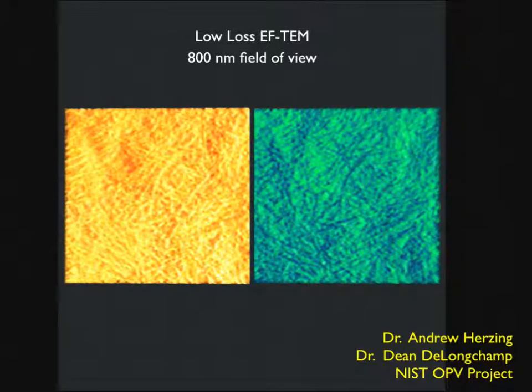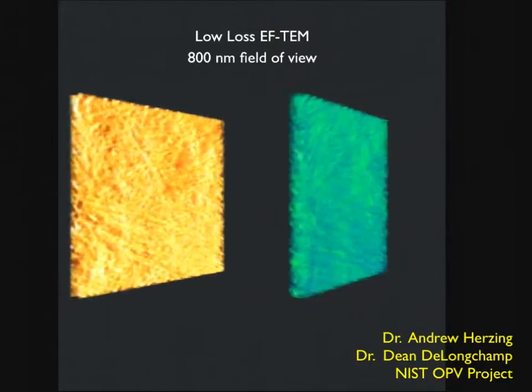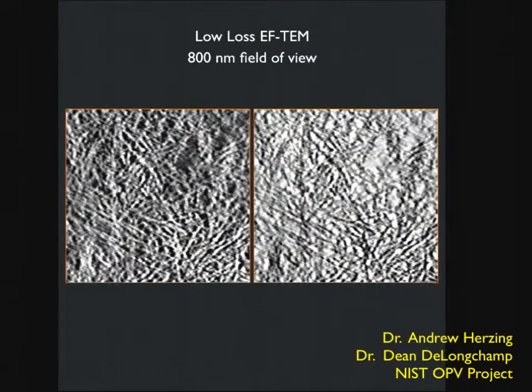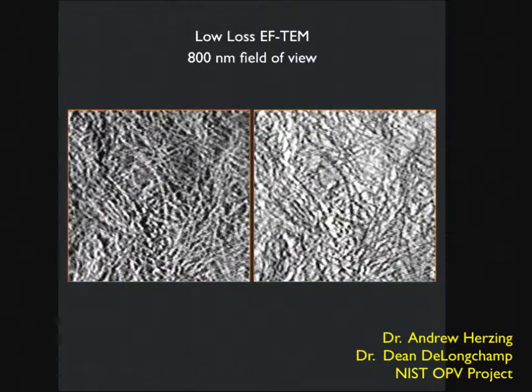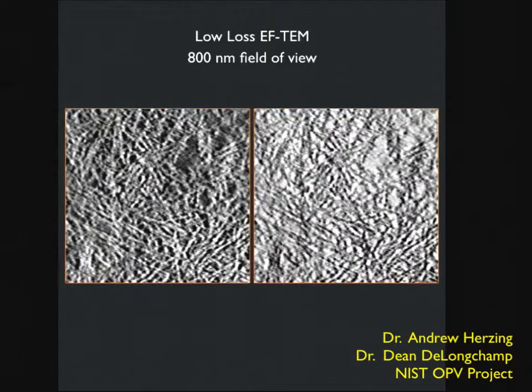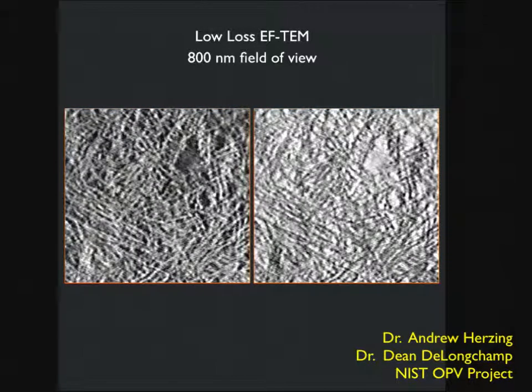Thirdly, the other thing we're unsure about is how to achieve a given morphology. So I showed you these molecular structures. We process those either through vacuum deposition or through solvent processing. We don't know in the beginning what this structure will look like at the end. So that structure-property relation is one of the big mysteries in the field. But nonetheless, through some intuition and a lot of hard work, we can get morphologies that do have nice charge transfer percolation pathways, and we can get charges out of the device. So in this TEM, we can scan up and down through the z-axis and get a good three-dimensional picture of the device.